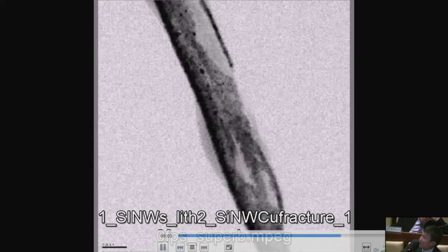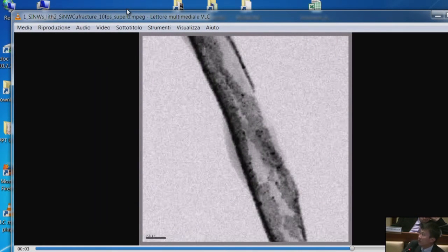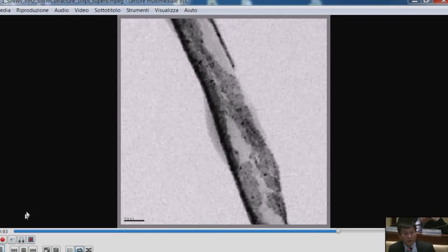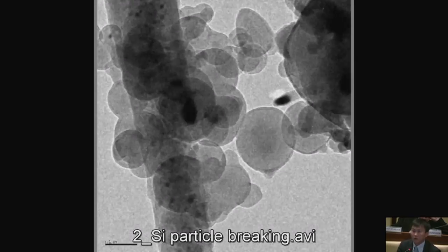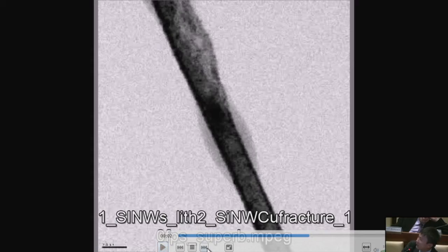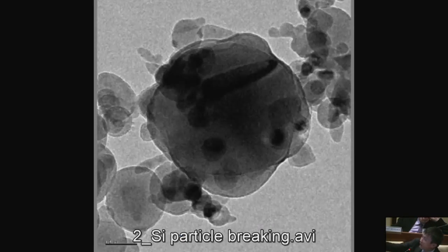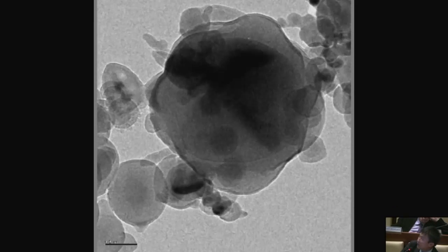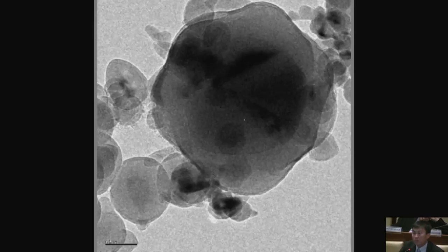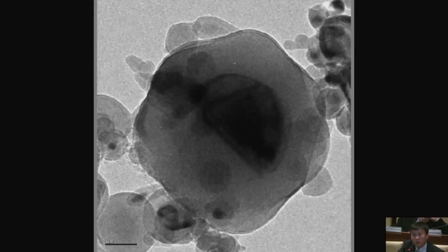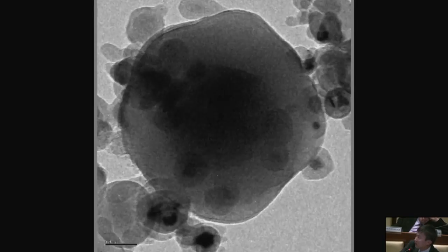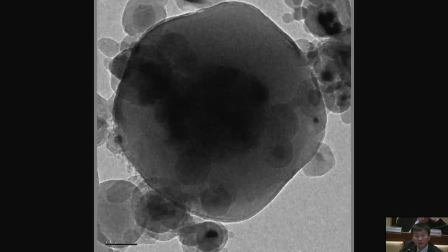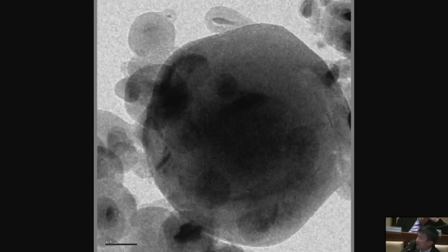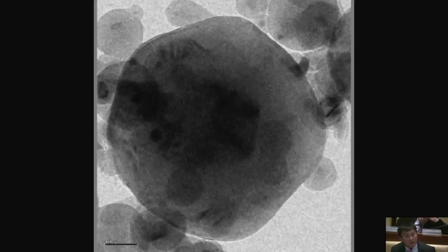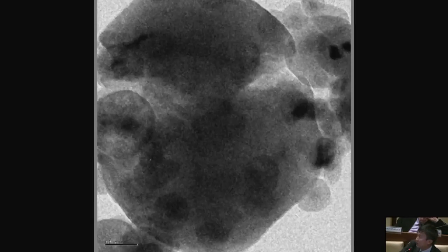You see when lithium going to silicon, the volume expands a lot. There's a copper coating on the surface. It's actually broken. So this volume expansion to about 400% of its initial volume. Let's look at this second one. Let's go to next one with the particle. This is a silicon nanoparticle that's diameter is 800 nanometer in diameter. When lithium coming in, you can see that big particle start to swell bigger and bigger. Eventually, there's too big of a stress building up. This particle cannot take this stress and get broken completely. Once this particle is broken, you lose electrical contact, you lose materials, the battery will die. You see the particle now is broken up.